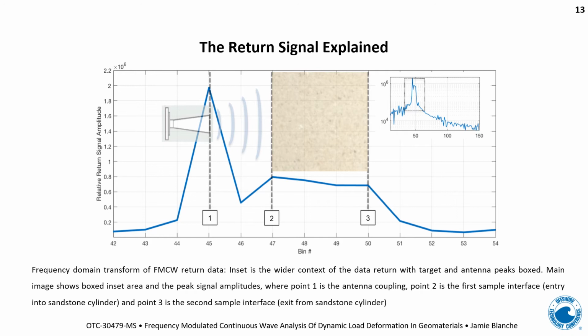The real data happens between point 2 and point 3. That's between bin 47 and bin 50. Remembering that these are distance measurements away from the antenna, between 46 and 47 is the end of the antenna to the target, which is about 10 centimeters. Well, it's exactly 10 centimeters, actually, we measured it. Then you've got bin 47, which represents that first interface into the sample, and bin 50 represents the exit interface of the sample.